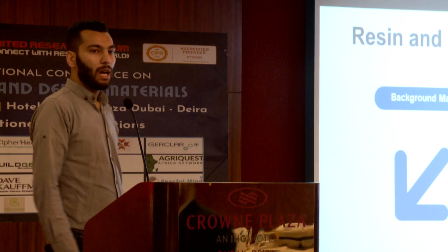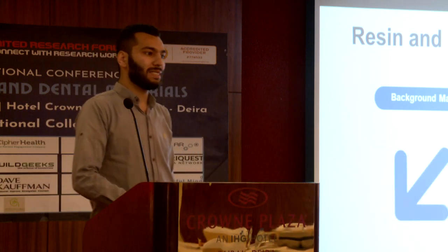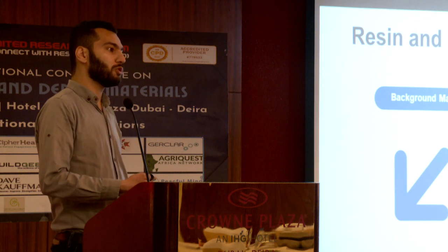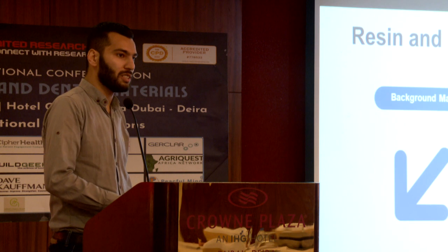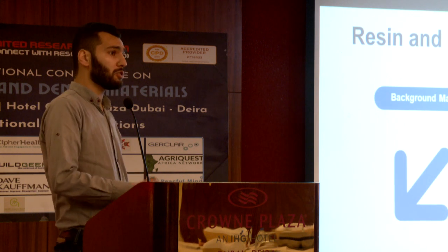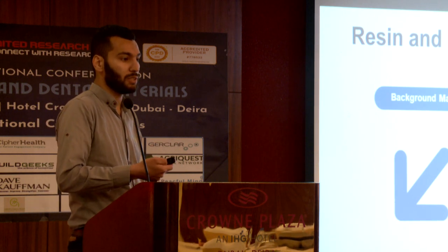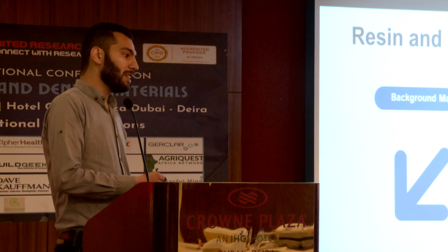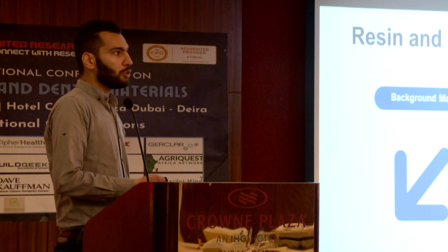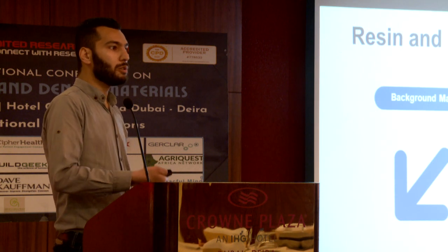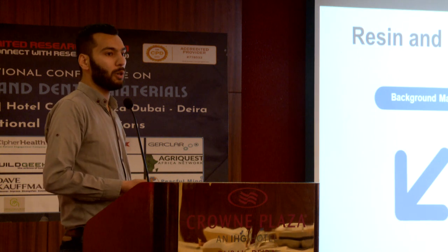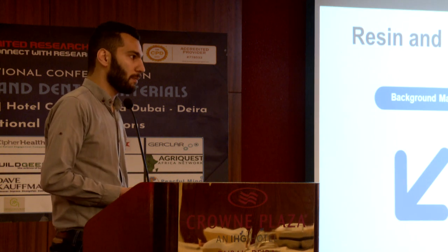Background masking, according to ISO, is related to translucency. But in dentistry, it's difficult to evaluate because according to ISO, we have to evaluate translucency of ceramic with 0.3 thickness on a dark background. In dentistry, we don't always use crowns or veneers with 0.3 thickness.